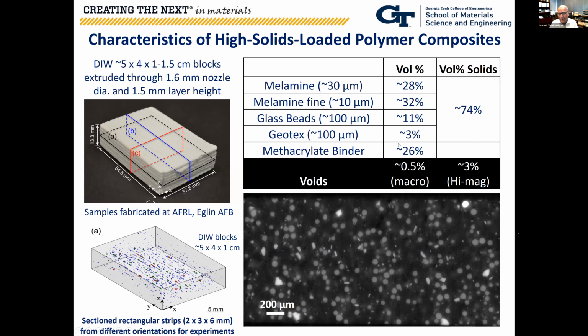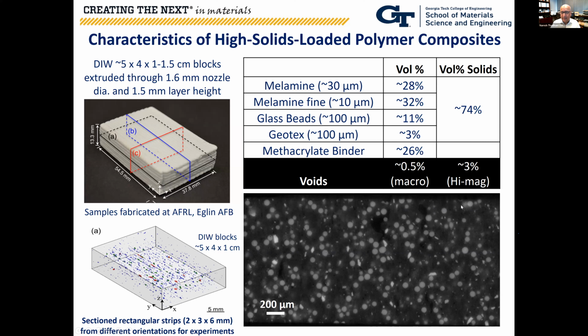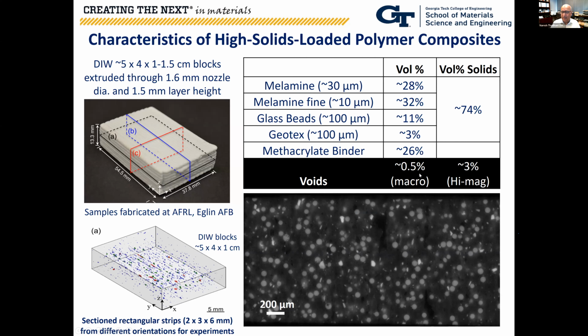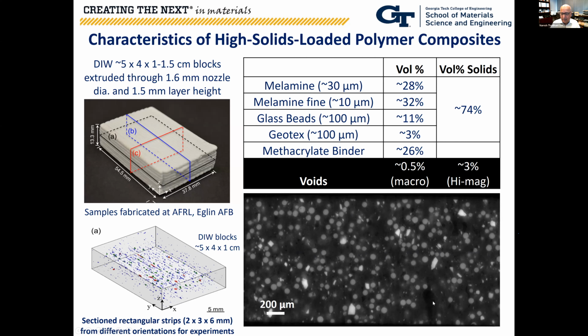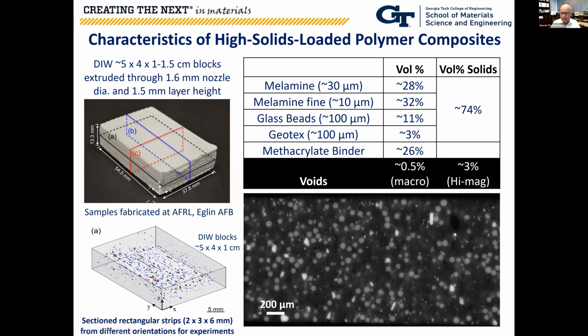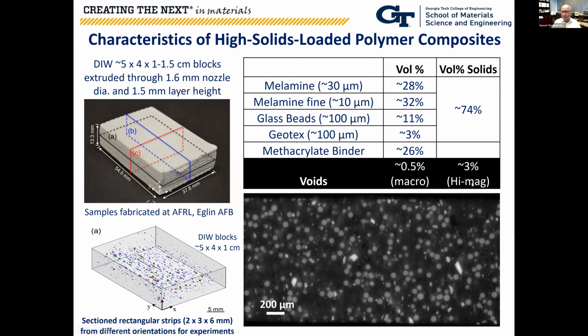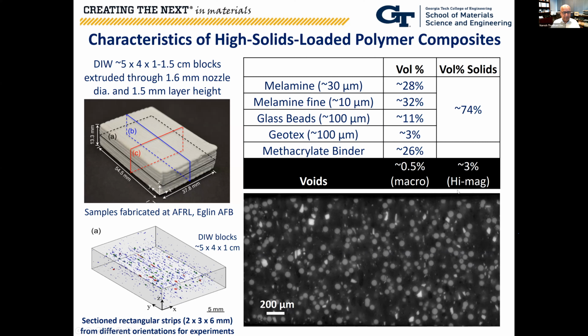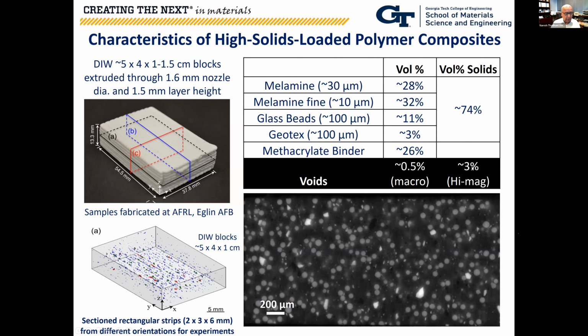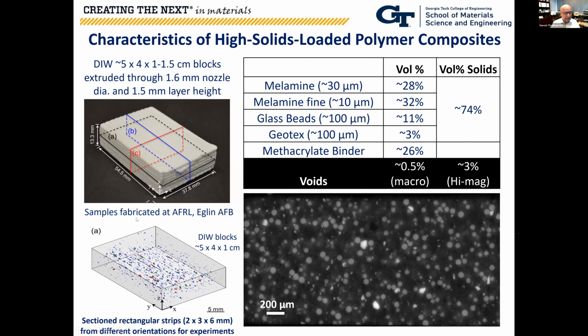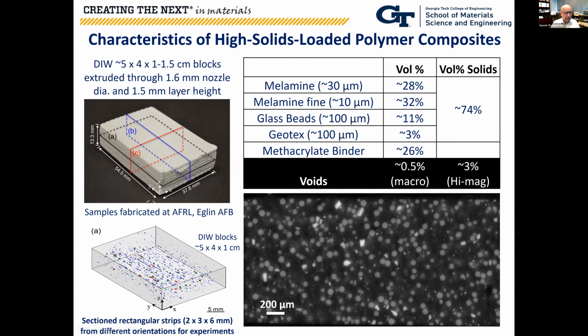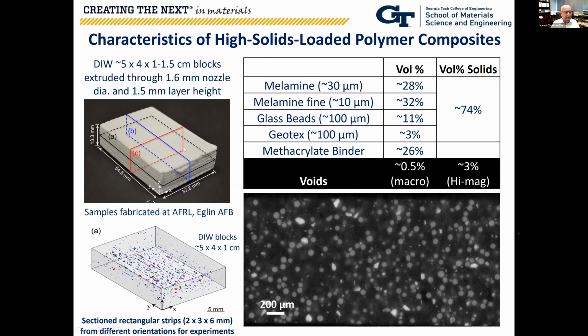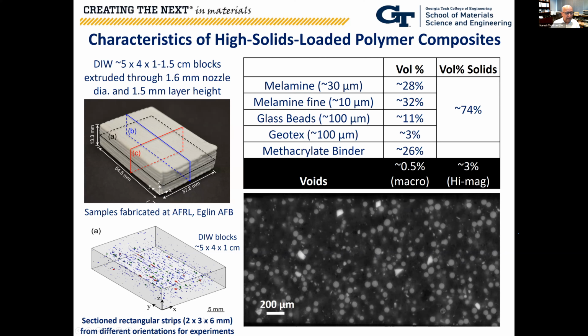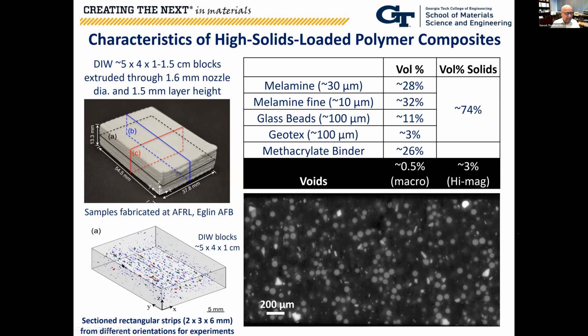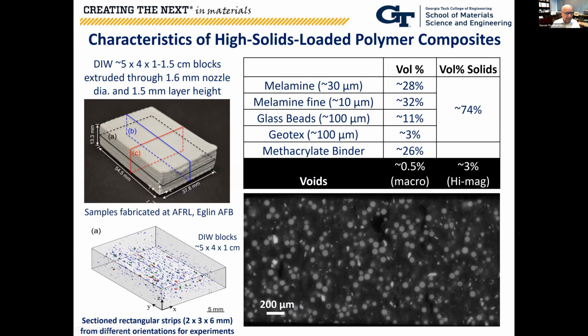The void fraction, if you look at the macro scale, is only about 0.5%. But if you zoom in at high magnification and take snapshots of these images, the porosity content shows up a little higher, about 3% or so. This image on the left-hand side shows you a CT of this entire block, and it gives you the directionality of the voids.